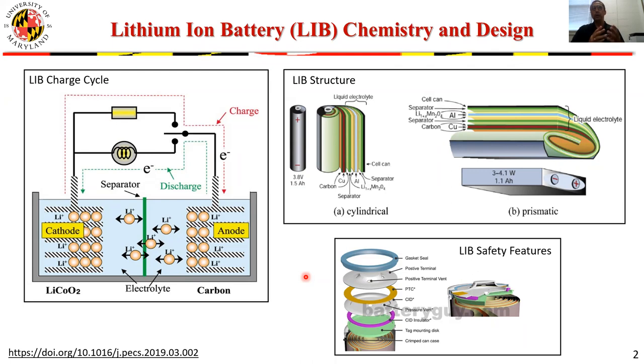The underlying chemistry of lithium-ion batteries, in very general terms, is shown on the left pane of the slide. I will walk through it without too much detail, just to give you a general understanding. A typical lithium-ion battery, when charged, has the cathode material subjected to an electrical potential that helps generate lithium ions and push them into the electrolyte. The cathode material is most generally an oxide of lithium and a transition metal or multiple transition metals. The most widely used chemistry is lithium cobalt oxide.